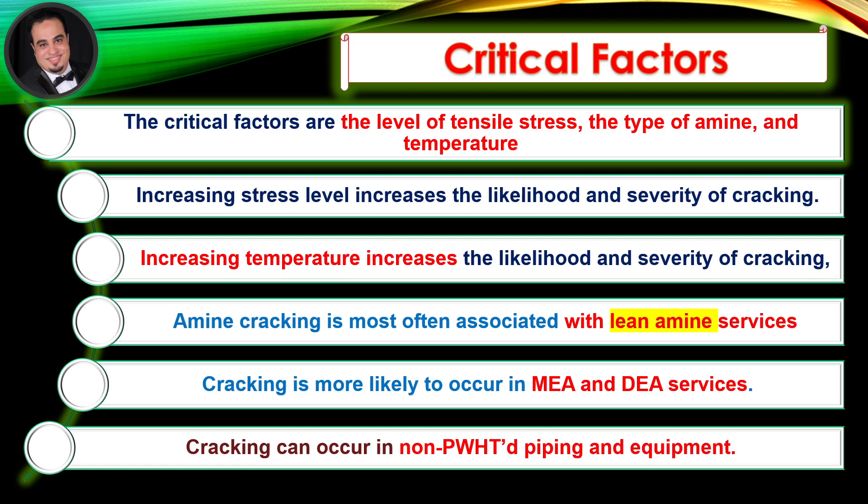Amine cracking is most often associated with lean amine services. Cracking is more likely to occur in monoethanolamine and diethanolamine services. Cracking can occur in non-post-weld heat-treated piping and equipment as the result of exposure to steam-out and to short-term amine carryover.